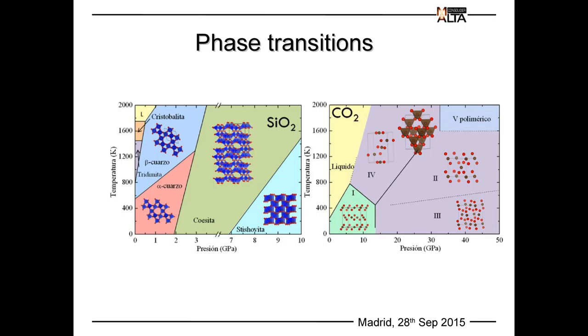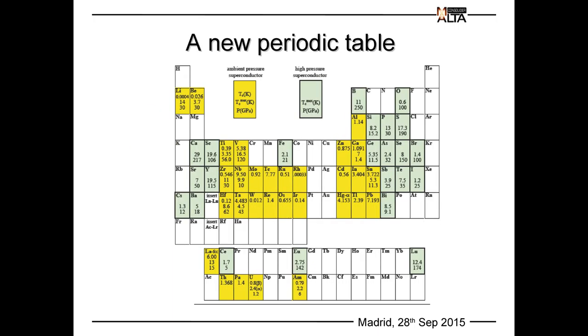We have phase diagrams showing polymorphism of silicon dioxide and carbon dioxide, with different polymorphs for each material. With pressure, you can turn an element into a superconductor. 23 elements become superconductors under high pressure, including iron and phosphorus. Pressure also increases the critical superconducting temperature of ambient-pressure superconductors. Most notably, it was recently confirmed experimentally that hydrogen sulfide is the superconductor with the highest critical superconducting temperature, around 200 Kelvin.